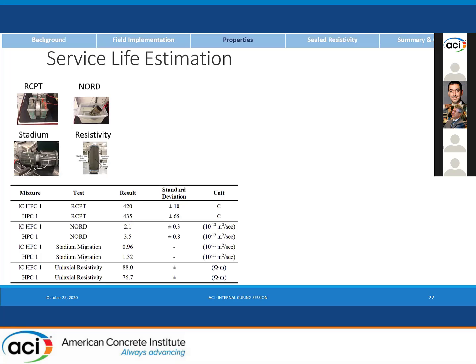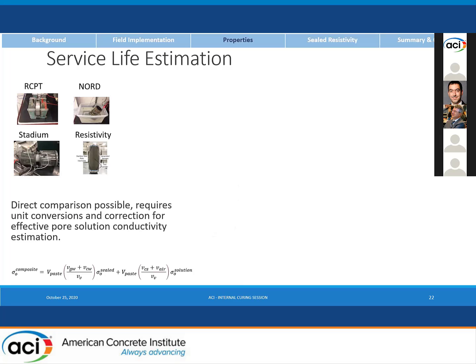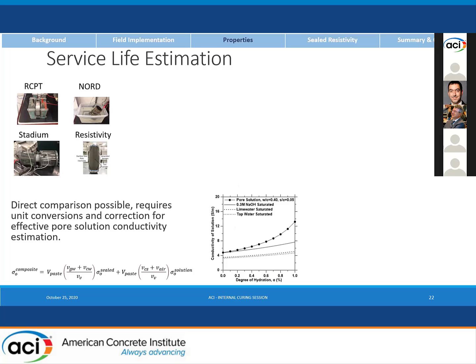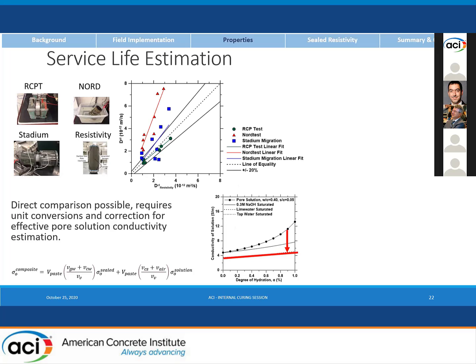But perhaps the question that's more interesting is, can we actually compare these? So I did measure the resistivity of all of these specimens before we tested them so that we had a consistent metric to compare them against. There are a couple of corrections for the fluid that you're saturating it with, so I've got that shown for you. And here is a plot, the resistivity diffusion coefficient that you get out of that method when applied appropriately versus the other methods. And so we see that the RCP test and the resistivity test give you exactly the same number. You can see that the Stadium test has a little bit of an offset, and that's because it is a migration test and they're making a back correction for the chloride binding, and then the Nord test does not make any such correction, so that's why it's on a different line.